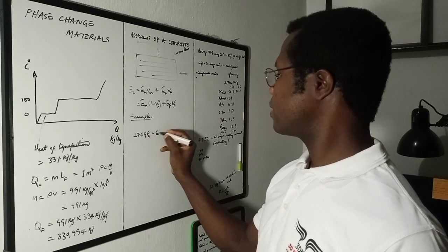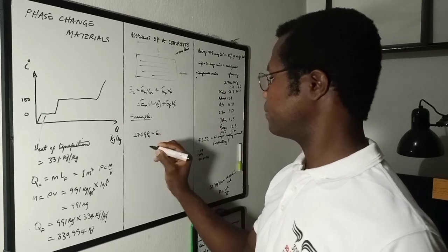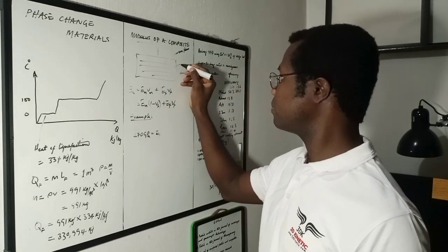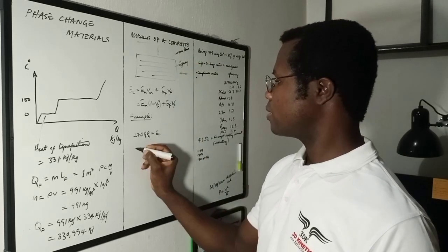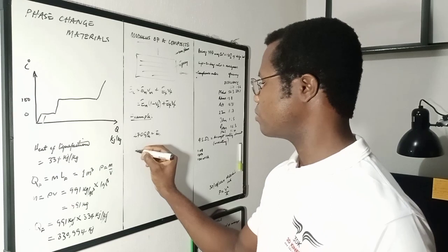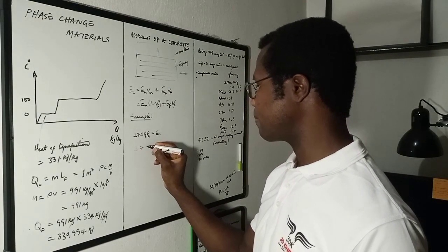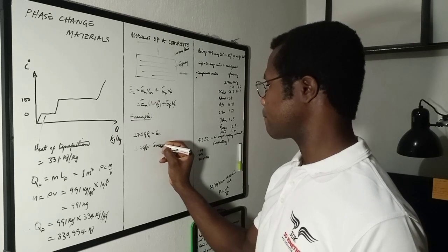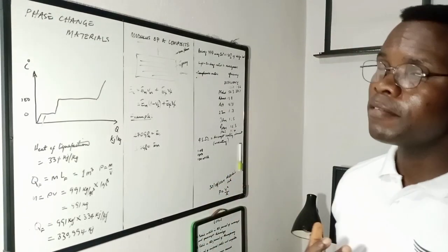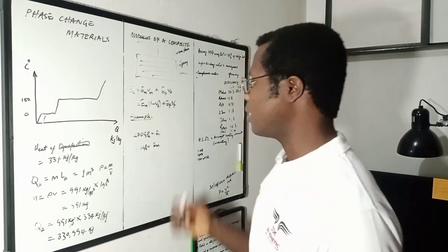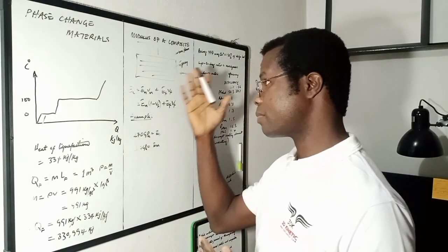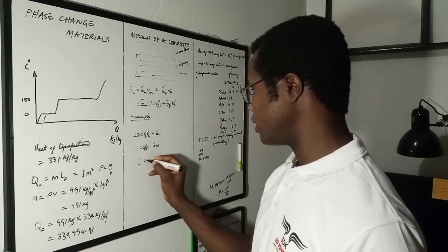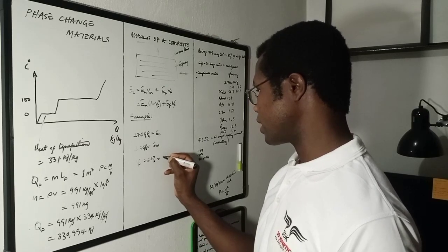So that's the modulus of the fiber. Then let's assume that the composite is made of a matrix of epoxy, and let's assume the epoxy has a modulus of 3.7 gigapascals. And then a volume fraction, let's assume a volume fraction of 60%. So 60% by volume of fibers making up the overall composite. So that means Vf equals 60%, which is also the same thing as 0.6.